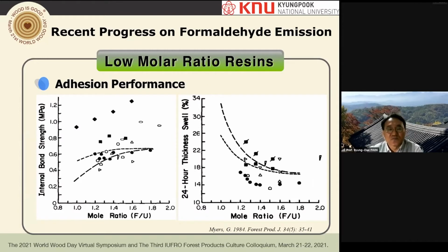And also, if you have the low molar ratio resin, you have low adhesion and internal bond strength, and also higher thickness swelling. That means if you have a low molar ratio, you don't have good properties.